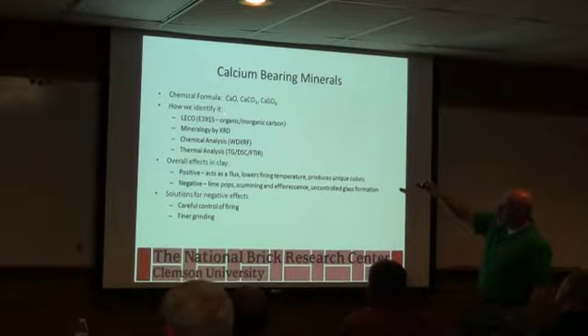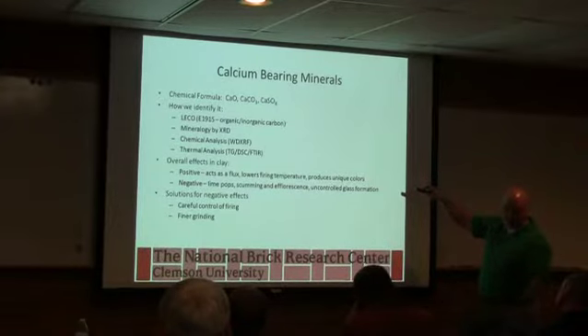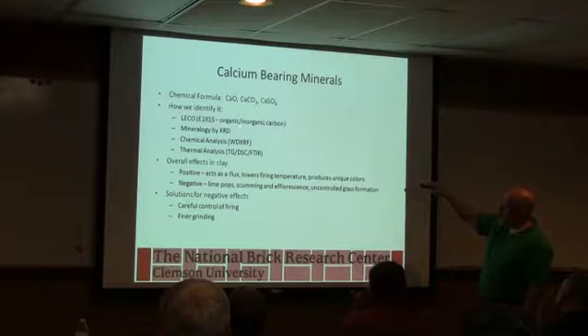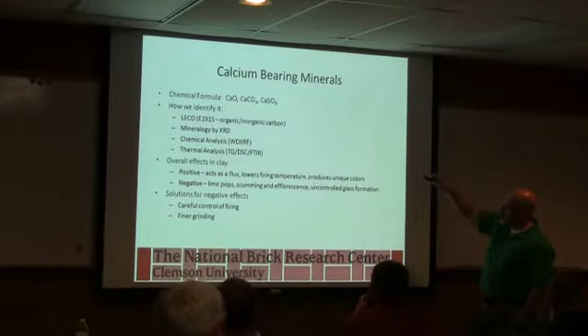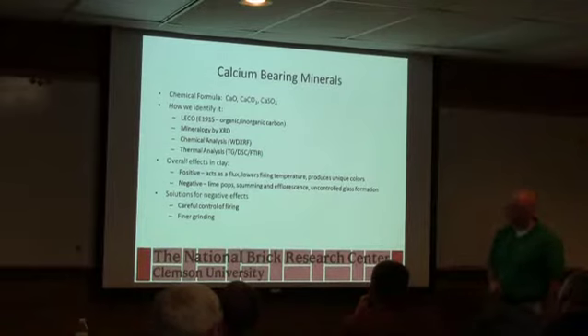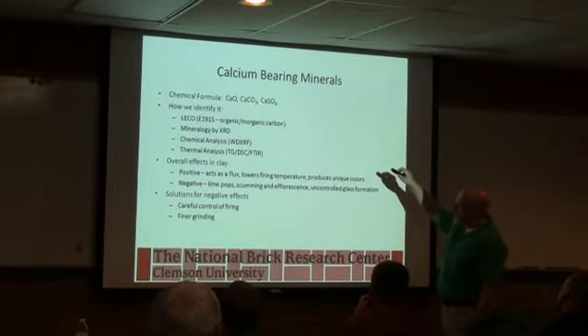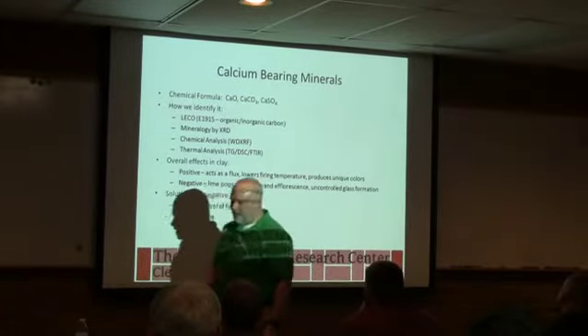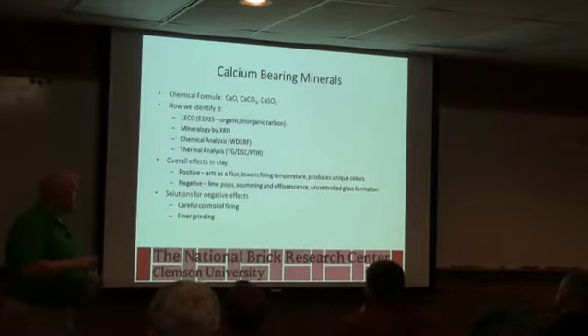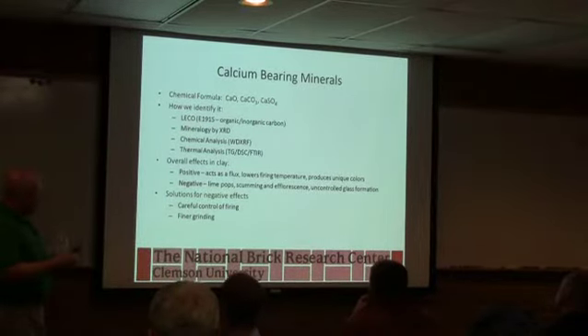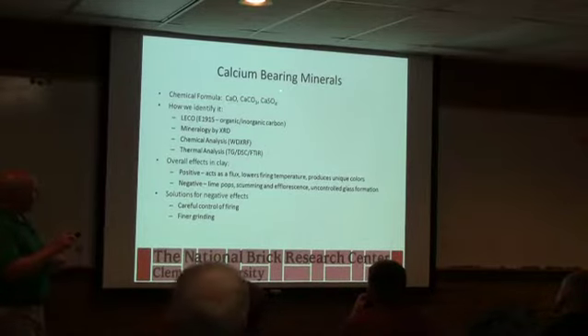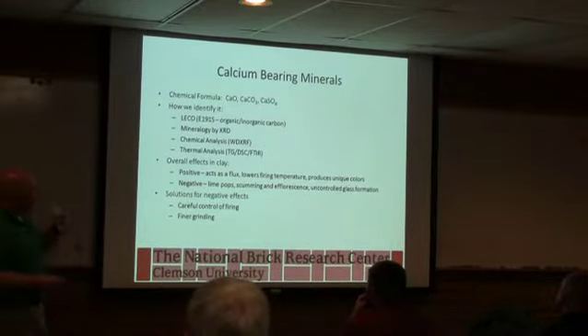So we can do a couple of things. The LOI, like we said, can give us some indication if it's there. LECO, just like what you have. There are ways to figure out what's organic carbon and what's carbon from carbonates, okay? Because this calcium carbonate is going to decompose in the latter part of your preheat going into your soak zone, and then calcium sulfate will start to decompose toward the end of your soak zone. It's pretty sluggish and hard to get rid of. If you leave the calcium sulfate behind, there's a good risk for efflorescence. That's the most common source of efflorescence.